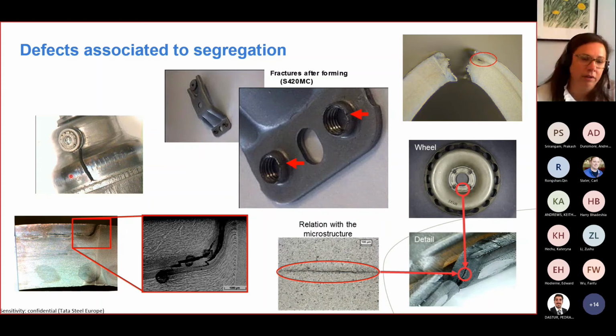For example, this is deformed and it has been cracked. Another example here, after forming, we have all this border that has been cracked in the same direction, with all little cracks due to segregation. How bad can segregation look? Well, it could look this bad. The differences in colors between here, the whites and the grays, are segregated areas and non-segregated areas.